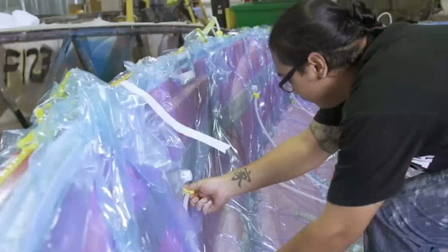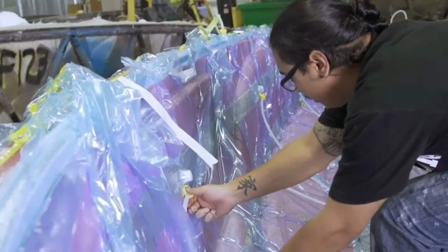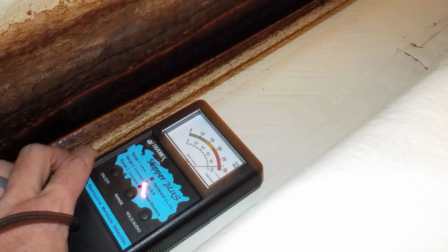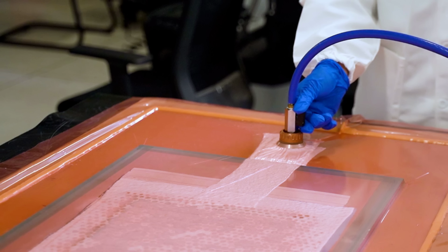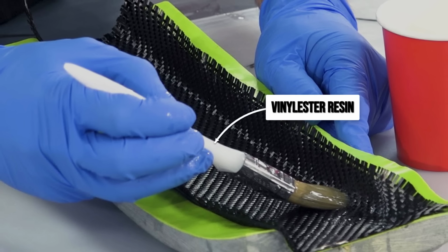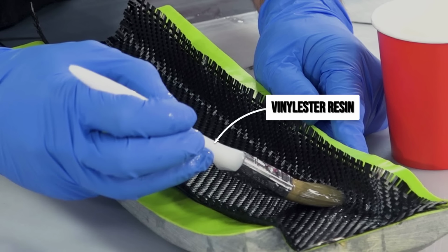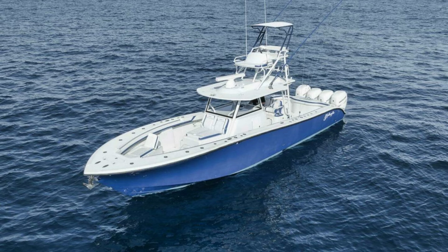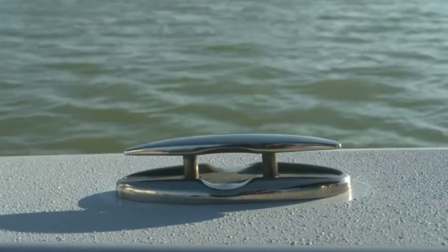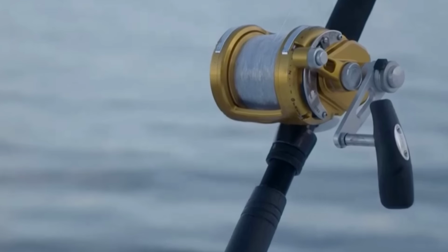Every Yellowfin hull uses 100% vinyl ester resin, confirmed by independent construction reviews. The lamination process uses vacuum bagging, pulling resin through the fiberglass under negative pressure and eliminating the air voids that hand lamination produces when quality control varies. It uses Baltek core in the running surfaces. There is solid fiberglass around all through hull fittings.